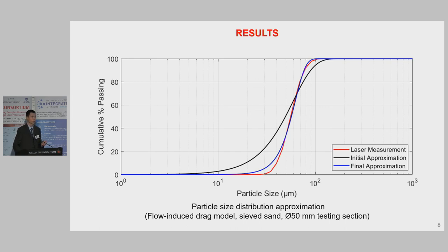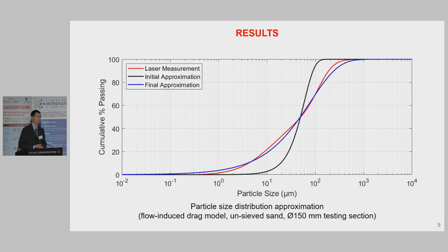Now the question again, is it the same case on a full-scale system? Yes. But this time, we can see some error at the coarser end. This is because when the particle size starts to increase, the particle probe impact starts to dominate, and that starts to introduce some error to the flow-induced drag model. So both the flow-induced drag model and the particle probe impact model should work together in order to obtain good approximation results for the size passing fraction for a target particle size. And the integration of these two models is what we are working on at the moment.